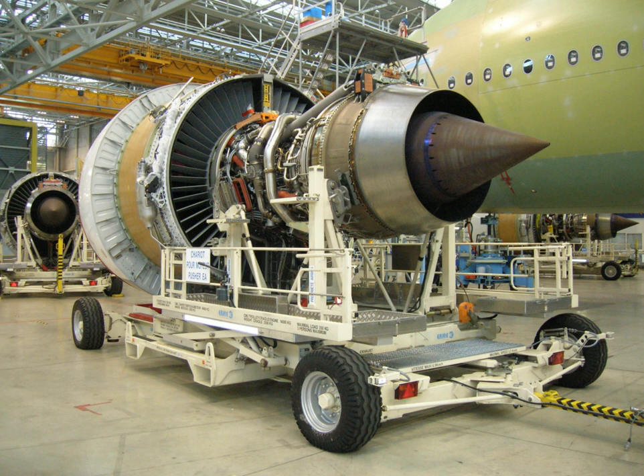Teething troubles may not show up until several thousand hours. The latest turbofans' technical problems disrupt airlines' operations and manufacturers' deliveries while production rates are rising sharply. Trent 1000 cracked blades grounded almost 50 Boeing 787s and reduced ETOPS to 2.3 hours down from 5.5, costing Rolls-Royce PLC almost $950 million.